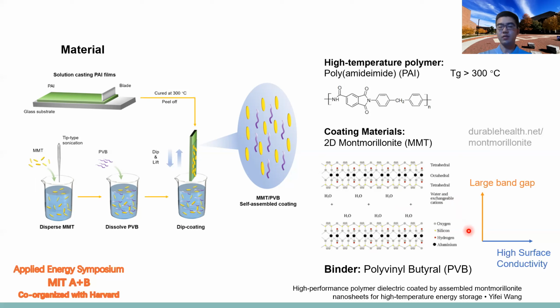If we check the band gap along the Z direction, we can find it has a very large band gap, and it makes MMT a very good insulator if we just utilize the Z direction property. But if we check the conductivity along the surface, we can find it has a relatively higher surface conductivity when compared with the Z direction. So this kind of unique anisotropic property is very useful if we utilize this 2D material for surface coatings, and its functions I will introduce later.